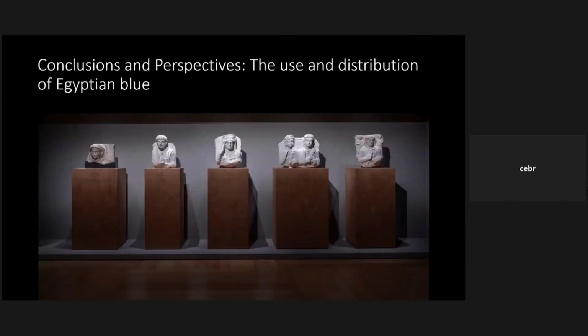So this case study has shown that, interestingly, Egyptian blue has not been attested on the more than 20 or so Palmyrene portraits examined by VIL in the Glyptothek, nor on the 7 thoroughly examined portraits. And in fact, lapis lazuli is to date still the only ancient blue pigment identified on Palmyrene sculpture. It's important to mention that all surveyed portraits have not been cleaned, but have preserved visible traces of polychromy.